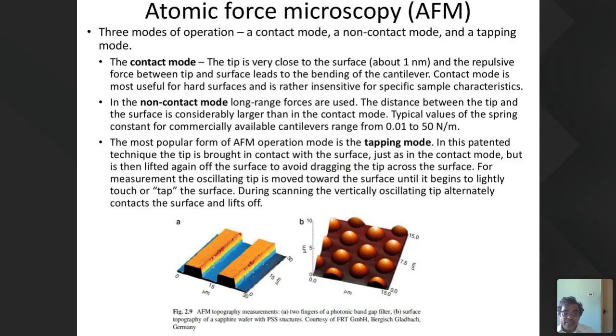Here there are also 3 working modes. One is contact mode, non-contact mode, and tapping mode. Out of these modes, tapping mode is more popular. In contact mode, the tip is very close to the surface and the repulsive force between the tip and surface leads to the bending of the cantilever. Contact mode is more useful for hard surfaces and is rather insensitive to specific sample characteristics.